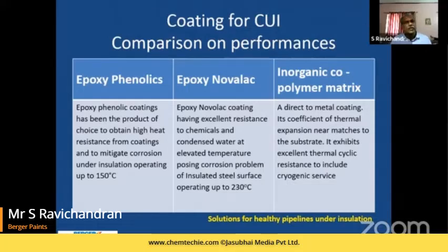Epoxy phenolics normally take care of temperatures of around 150, whereas with higher temperatures, we will not be in a position to maintain, or the thermal cyclic resistance is not going to be more effective in the case of epoxy phenolics, either by increasing DFT or by having a higher temperature range. But epoxy Novolacs had exhibited excellent resistance not only to the heat, but also to the chemicals and to the condensed water at elevated temperatures, and it was able to handle up to 230 degrees centigrade.